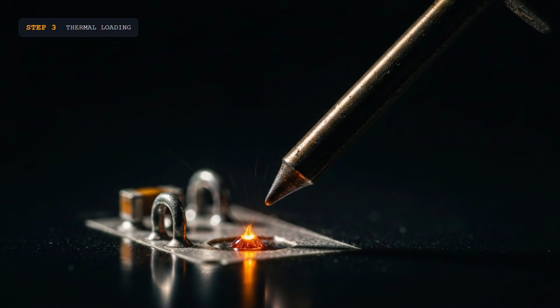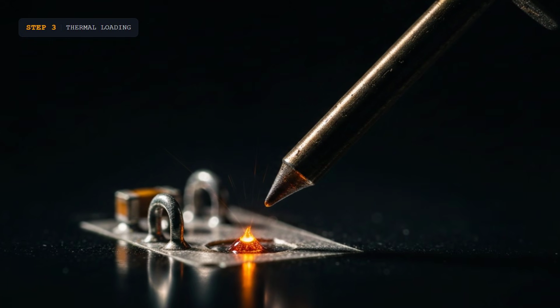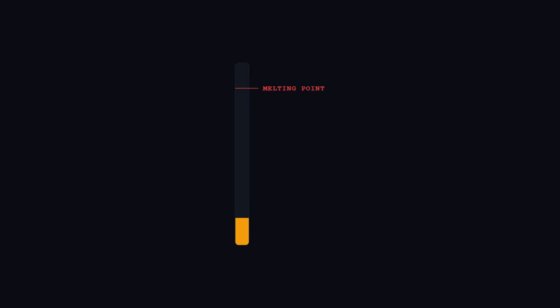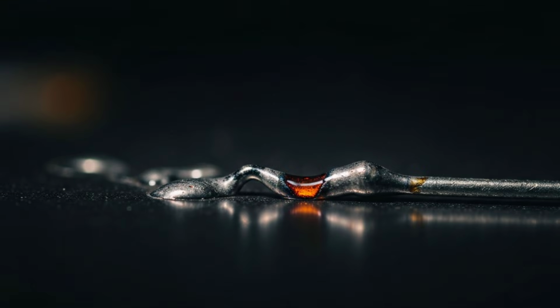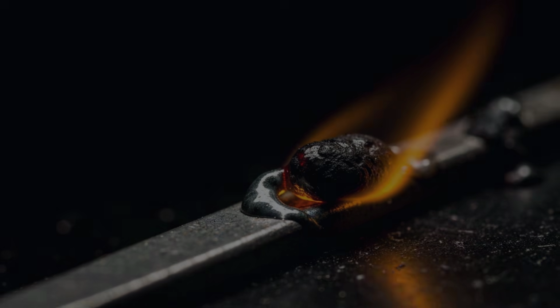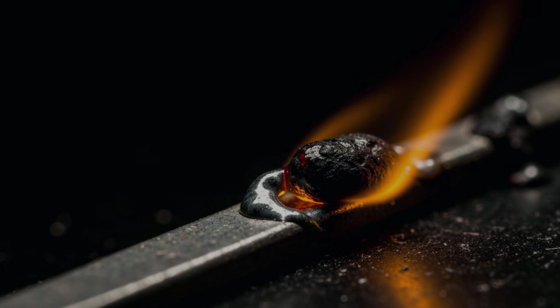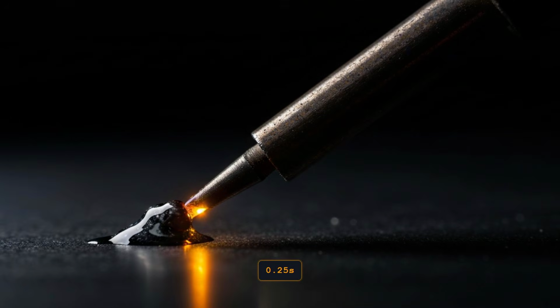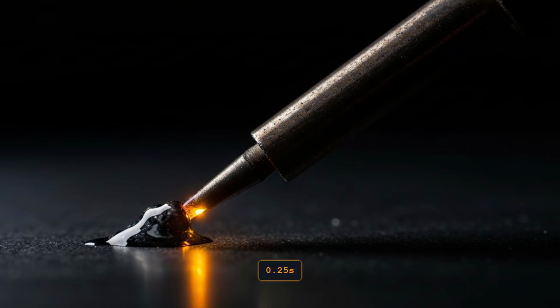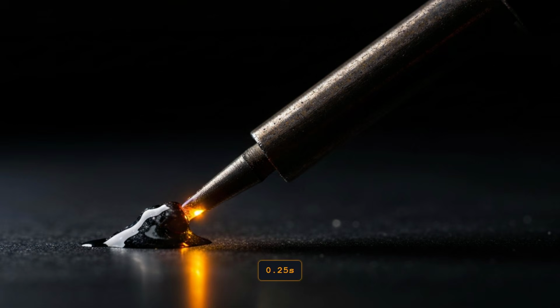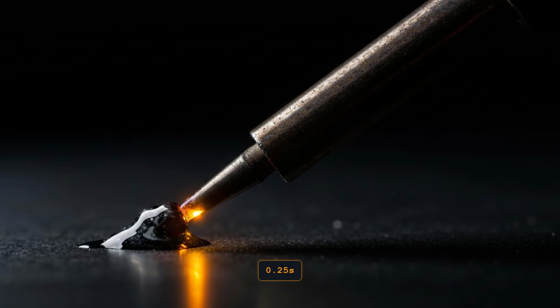The iron doesn't touch down and melt anything on contact. Step 3 is about loading heat into the pad and the component at the same time, climbing toward the solder's melting threshold, degree by degree. Too fast, and you shock the component. Too slow, and the flux burns off before the metal is ready. There's a narrow window, and it's measured in fractions of a second. The same fraction of a second that separates the 2 joints from the top of this video.